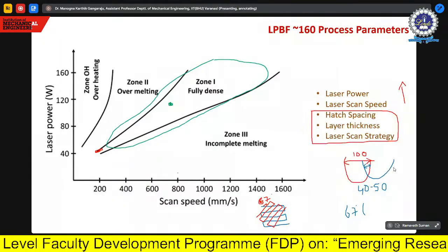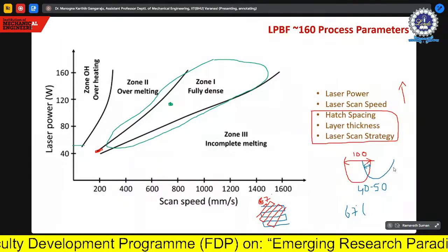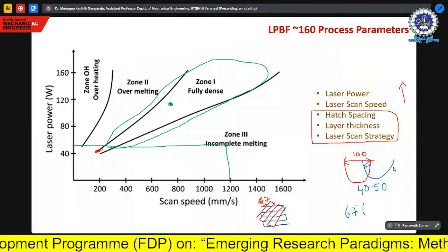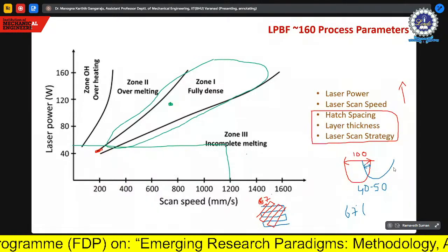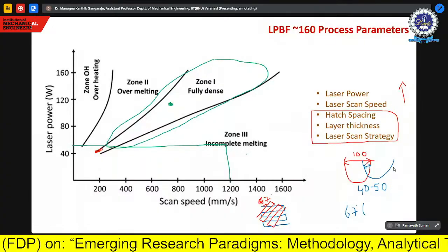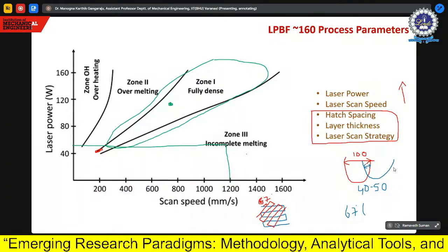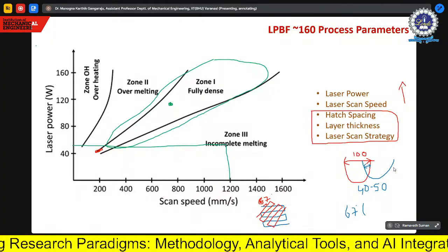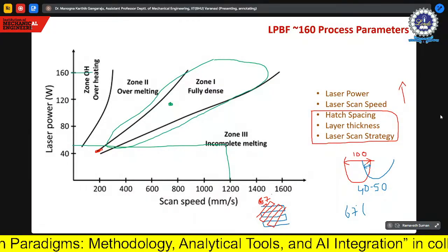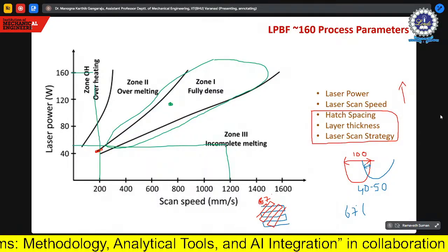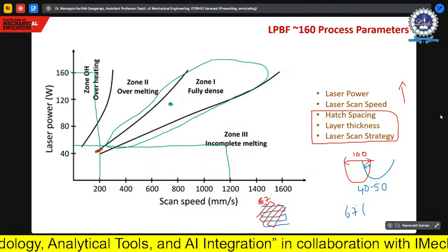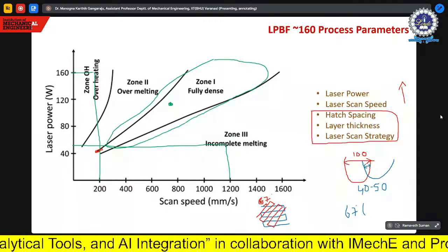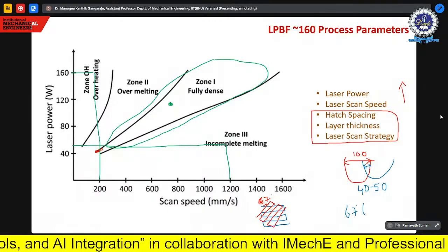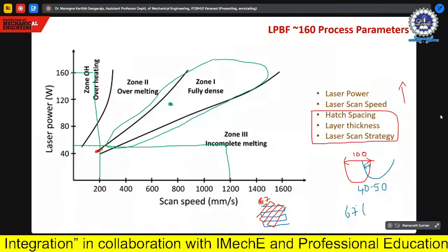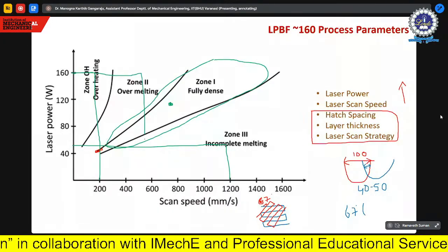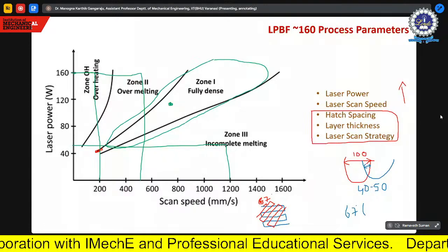Okay, in this region, because you are at a very low power and very high scan speed, the heat source is not very hot, or the melt is not happening. So that's why incomplete melting. In this case, because you are having very high power and very low scan speed, you are overheating. The same region you are staying for a very long time because your scan speed is very low. Then you end up having overheating. In the same case here also, till a particular scan speed, you have overheating problems.